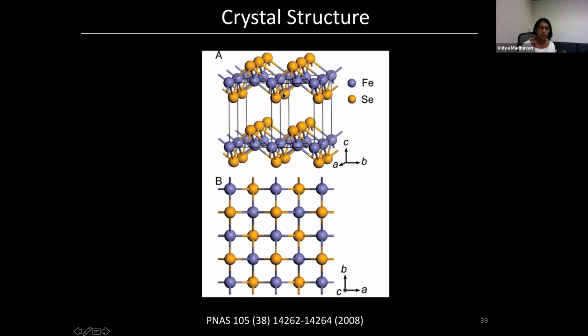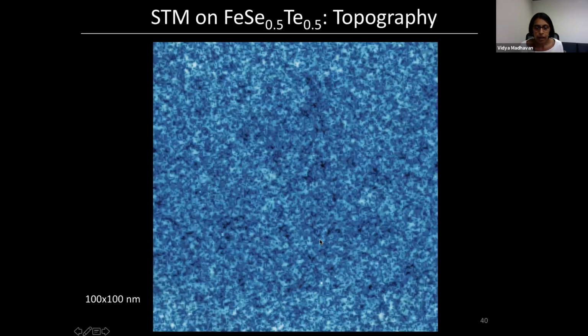from the layer below. Now, because STM is mainly sensitive to the surface, if you do STM on the surface of this crystal, for example, what you'll see is the selenium or tellurium atoms, which is going to form a square lattice shown here. Okay, so these are the ones in the layer below, right? And the purple ones are the iron atoms. We don't see any of that. So this is what topography would look like with a scanning tunneling microscope.